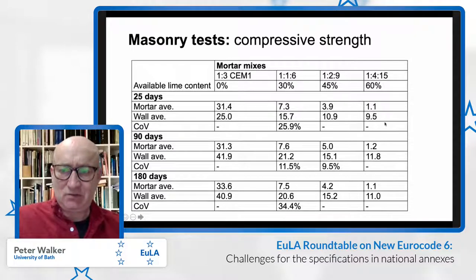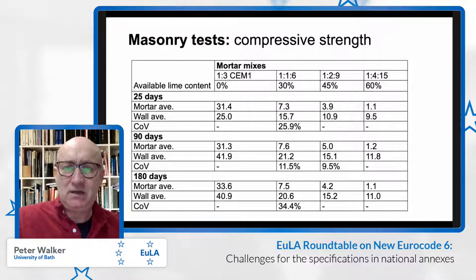One thing that we picked out, and I think as Meera and others have noted, is that whilst the mortar strengths have reduced, say at 25 days, from 31.4 newtons per square millimeter down to 1.1 for the weakest mix, the reduction in the strength of the masonry does not follow that trend. This is well known, the complex interaction between the masonry units and the mortar in governing the mechanical performance of masonry. So the reduction in strength of the masonry is significantly less, which illustrates the potential for using lower strength lime mortars and still retaining a good level of strength in the masonry.